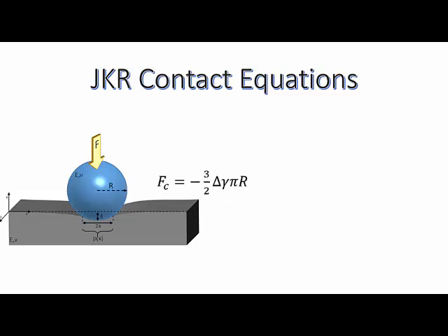This means a stiff surface and a compliant surface will be just as sticky provided that they have the same surface energy. In fact, this force varies linearly with only two variables, work of adhesion and sphere radius, making it simple for us to calculate the adhesion in such a non-conformal contact.